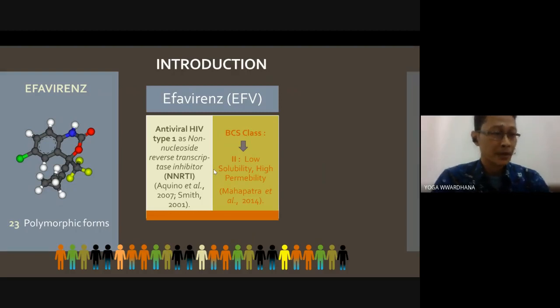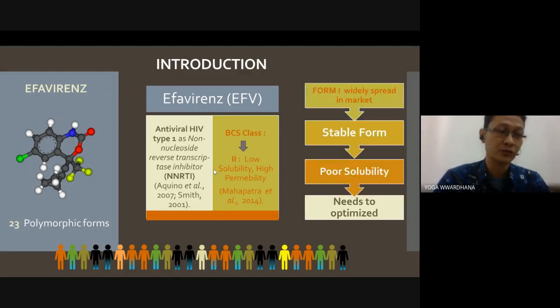Efavirenz. But it has a rate limiting step in solubility because it is BCS class 2 with low solubility, around 3 microgram per milliliter, and a low intrinsic dissolution rate of 0.037 milligram per centimeter square per minute. The market uses the stable form of efavirenz, which, as we know, has limited solubility compared to metastable polymorphic ones. So we already studied improving the solubility via other forms.